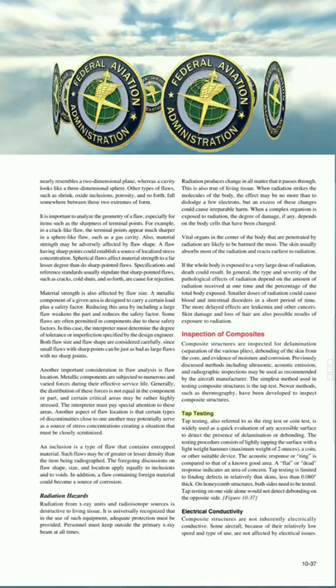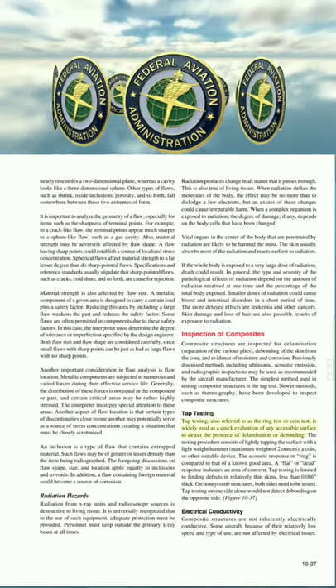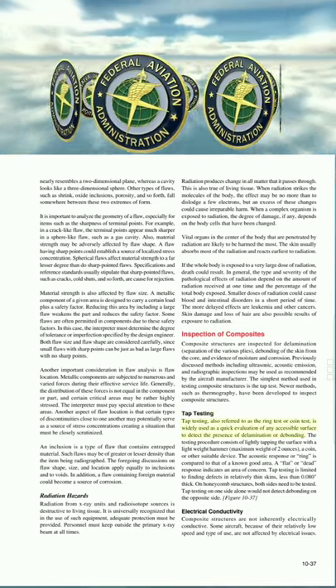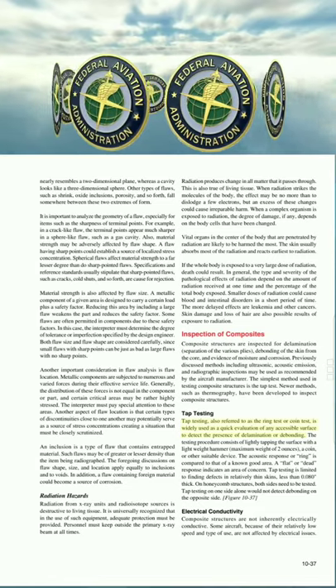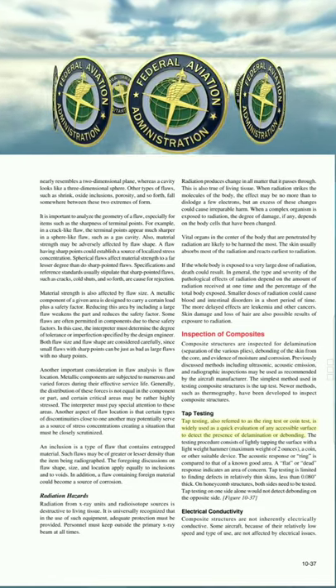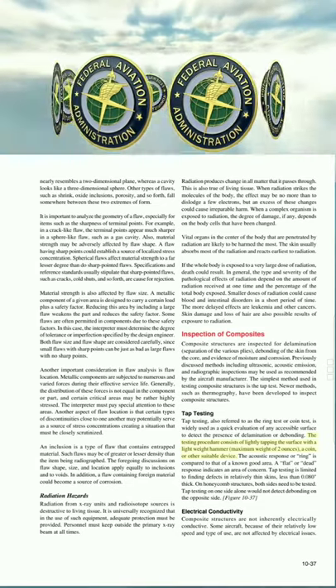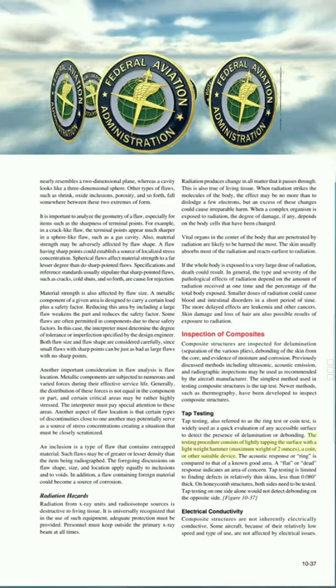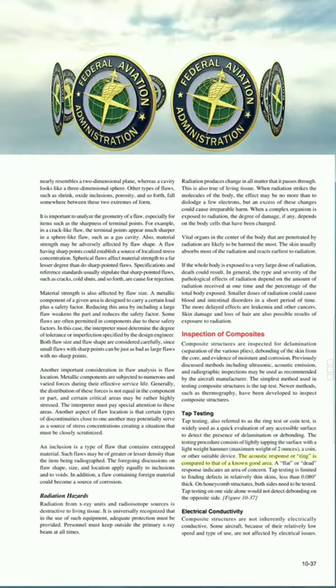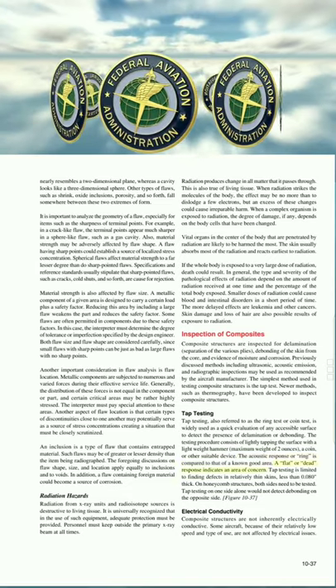Tap testing. Tap testing, also referred to as the ring test or coin test, is widely used as a quick evaluation of any accessible surface to detect the presence of delamination or debonding. The testing procedure consists of lightly tapping the surface with a lightweight hammer, maximum weight of 2 ounces, a coin, or other suitable device. The acoustic response or ring is compared to that of a known good area. A flat or dead response indicates an area of concern.